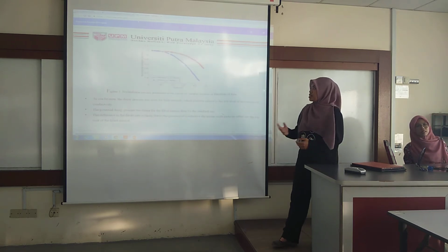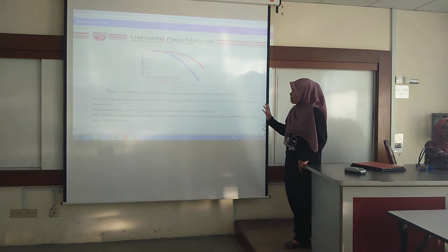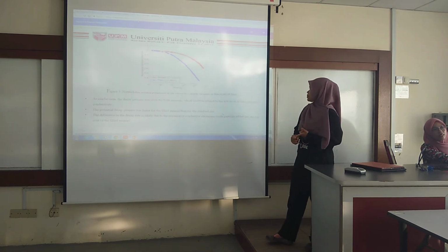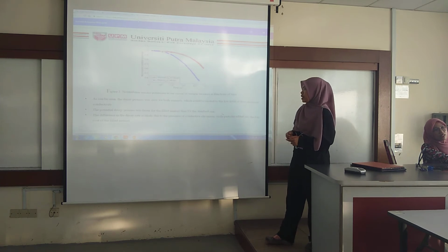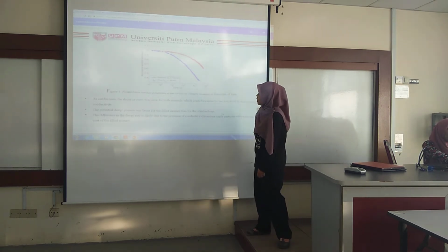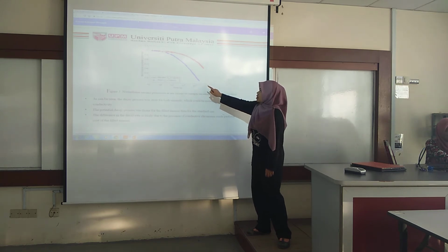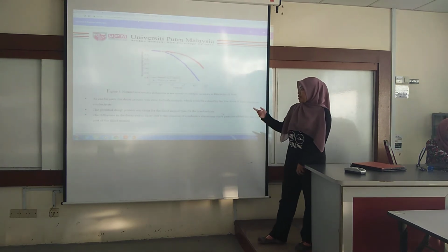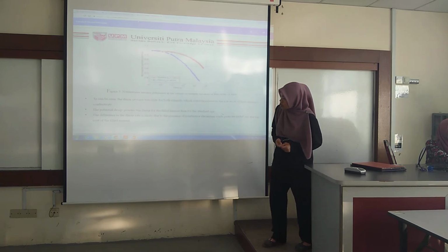This is the result based on the experiment. We can see from this figure that the decay process was slow for both enamels, which can be related to the low level of dielectric conductivity. The potential decay process was faster for the pale enamel than the standard one. You can see here, at time 10 to the power of 5, the pale enamel is almost at 50%, and the standard is about 80%. The difference in the decay rate is likely due to the presence of the conductive chromium oxide particles added into the top coat of the pale enamel.